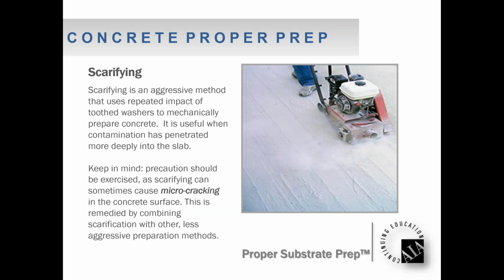Scarifying is another method of prep, not so commonly used. Typically, it's just outside, even though they do have electric scarifiers. You see this one's obviously gas run, so you're not going to operate a gas machine in the interior of a building. Scarification consists of star-like washers, and maybe you have about 30 or 40 of these star-like washers on an axle, and maybe you have 3, 4, sometimes 5 axles that will complete a rotation, and this spins towards the surface of the concrete, and you dial those spinning arms down towards the surface of the concrete, and it physically is ripping the surface of the concrete. The problem with scarification is it can create microcracking in the concrete. So while it is a mechanical method, present day it's not quite used as much. Shot blasting and grinding are the 2 common methods of mechanically preparing concrete.